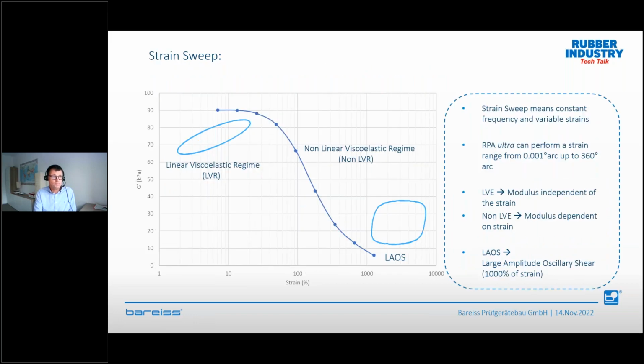So the next one would be the strain sweep. In the strain sweep, the frequency will be constant, for example at 1 Hertz or 1.67 Hertz or 0.1 Hertz, and we make variable strains. For example, here we go from a very low strain up to a very high strain. Then you see a typical curve of a strain sweep. It's G prime, the shear modulus, as a function of strain. At a very, very low strain, the modulus is independent of the strain.